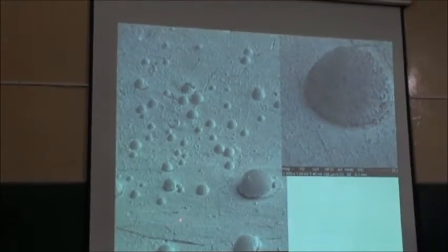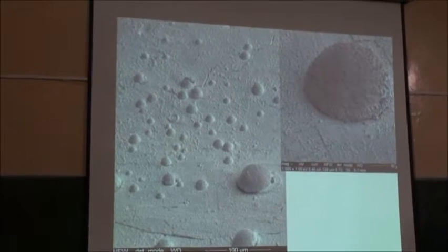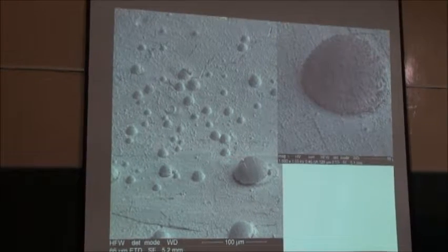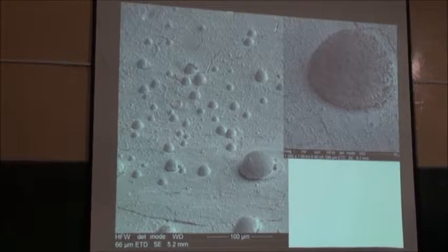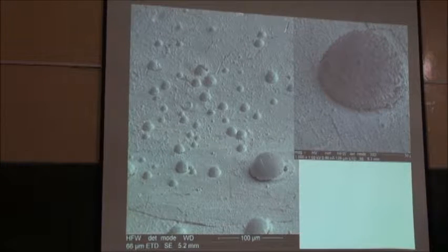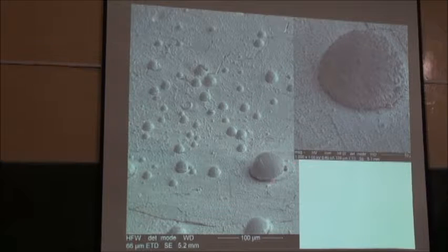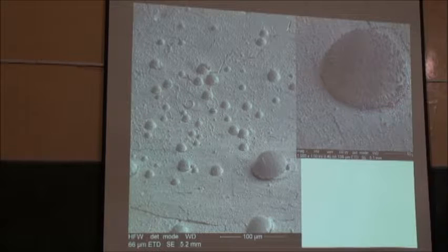So that's the picture you can get from SEM, and that's interesting because the print definitely corresponds to something above and not below. Also, you see there is some detachment of water droplets, and this detachment is due to the fact that when you freeze, the thermal expansion of the water is different from cyclohexane, so this can detach. But that's interesting because you can see the shape, and this corresponds to the liquid cyclohexane around the droplets. So that's another view.